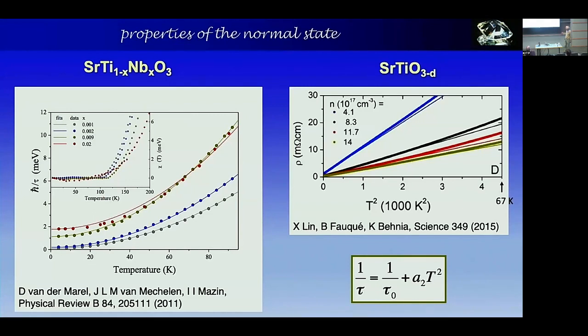And the lines are a fit, assuming that you have T squared plus some background, plus some residual scattering. And so this is T squared. That fits very well for all cases except for the highest doping, where you see there's a bit of a deviation. You would actually need to put in a T cubed additional term to get a better fit. This T squared was further analyzed in another paper by the Behnia group. Here it was displayed as a function of T squared. They have many more panels. I just show this one here.